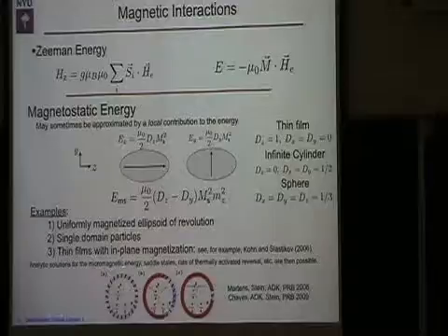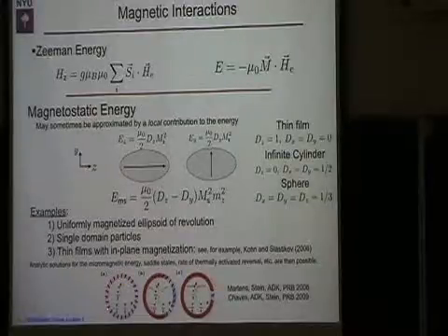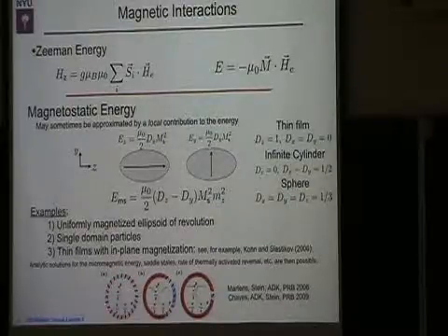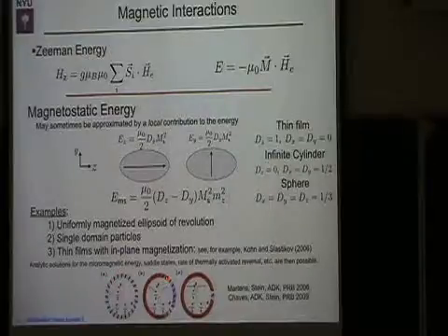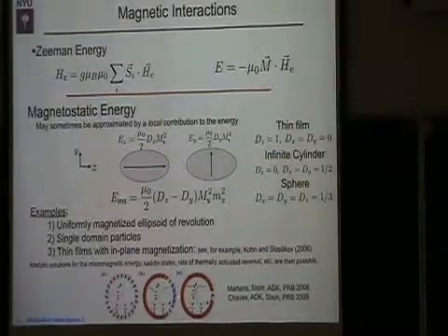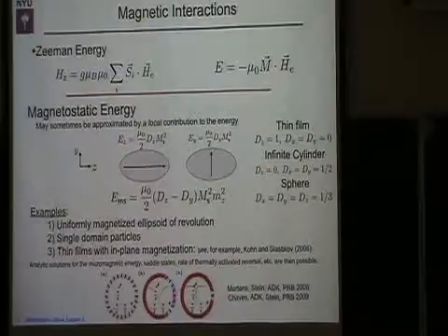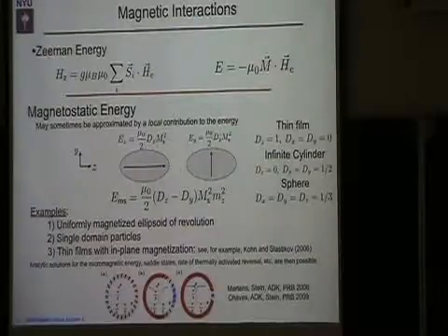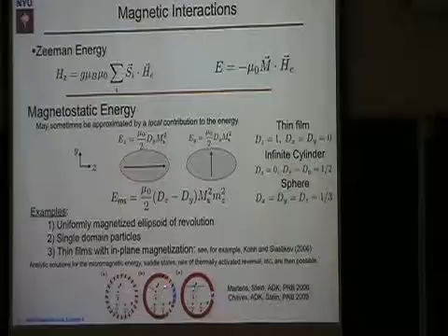These are some of the pictures of the transition states, where you have a thin, soft ring, which can either be magnetized clockwise or counterclockwise. You can have either a metastable state that's a global rotation of the magnetization at some angle, or a soliton, where a localized fluctuation forms, and then will expand. So that's kind of a neat thing. When you can approximate these by local interaction, you can really come up with models.